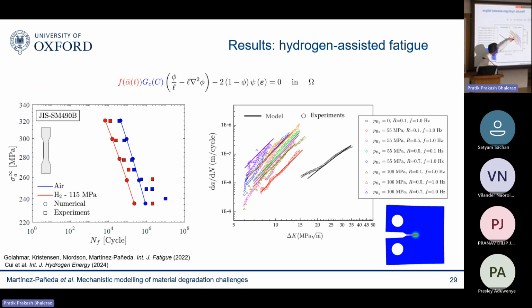we calibrated the fatigue degradation function with response in air, and then we predicted hydrogen-assisted fatigue for a very wide range of environments, different hydrogen pressures, different load ratios, different frequencies. So here, there's no recalibration of the model. We are basically just changing the load ratio, the frequency, just the way we load our model. There's no fitting involved in any of these results.